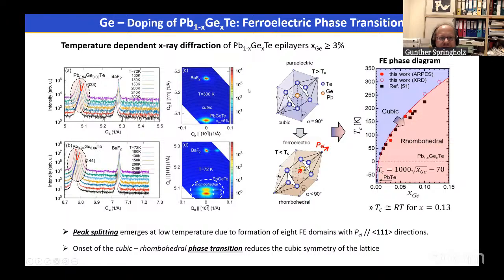And so what we see when we do X-ray diffraction as a function of temperature is shown here. Here we're looking at the 333 Bragg reflection of lead germanium telluride, and from black to purple, the temperature is lowered from 300 Kelvin to 70 Kelvin. We see that at some temperature, the peak starts to split into 2 peaks. This is also shown here in the reciprocal space map, where at low temperature, the X-ray peak of lead germanium telluride is split in 2, whereas at room temperature, there is just 1 peak.